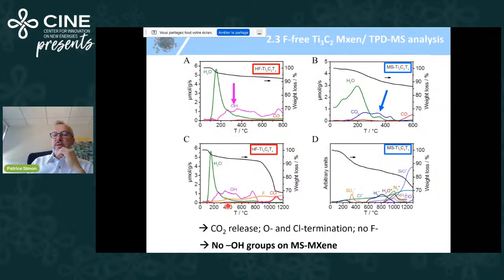But what is interesting as well is that we tried to analyze the surface group composition of the MXene. So here on the left side, this is MXene prepared from HF, from 0 to 800 degrees Celsius. So we heat, we make a TGA, in fact. But at the same time, we have a mass spec, and we can know what gases are emitted, and we can go back to the surface functional groups present on the surface, depending on the temperature of decomposition. So here, you see that on HF MXene, you have mainly water and OH groups.